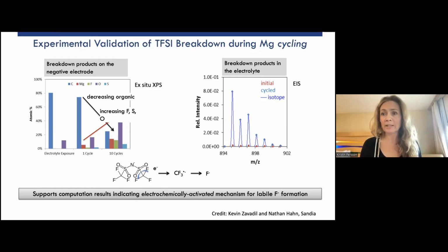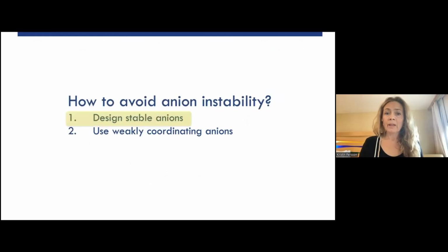that breaks down TFSI. It's not just the exposure of a platinum surface polarized to magnesium potentials. And they were also able to see through spectroscopy of the bulk electrolyte that there were fragments that corresponded to this sort of C-F breakage, which again indirectly corroborated the modeling predictions. Okay, so we had a hypothesis now that the difficulty in designing multivalent salts originates partially from this multi-electron transfer process, which can expose the solvation structure around the working ion to instability.